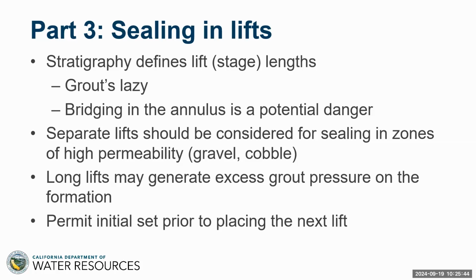We also have a phenomenon which we call sagging, which just means that before the grout has completely hydrated, it can drift away into permeable ground conditions. And you might not notice that by observing the grout at the top of the hole. So you might just be left with a hole in the grouting program halfway up the annulus, for example. And that's because the grout will bridge between the pipe and the ground condition higher up. So again, it may seem an overcomplication, but it should be driven by the ground. And if there is a potential danger for bridging or excess grout takes, then this would be the defense against it.